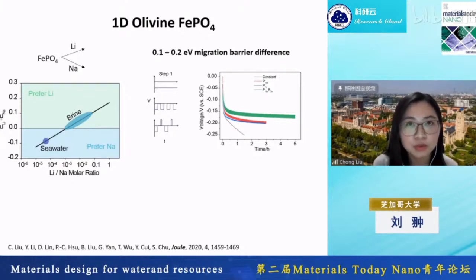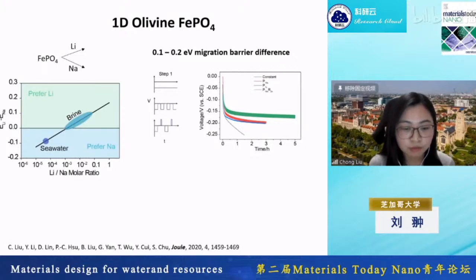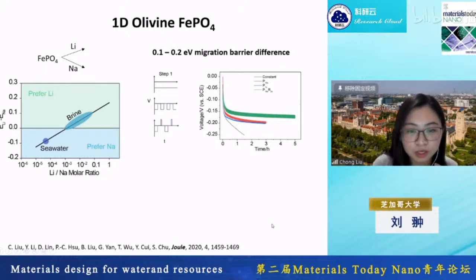You want to decrease your overpotential to let the thermodynamics play the role for the selectivity. But in the electrochemical process, we all know that if you run the current, the faster you run the current, the higher your overpotential would be. So that overpotential will balance everything, meaning that at some point, if your overpotential is high enough, then sodium wouldn't have enough energy to overcome its migration barrier and diffuse through the material and compete with lithium. So in this work, what we do is we try to select different kinds of intercalation patterns.